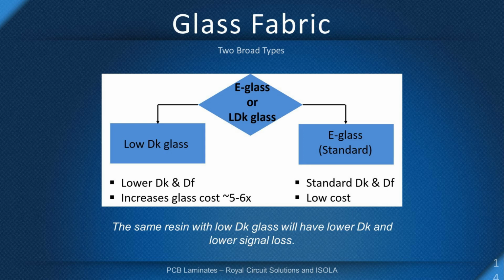All right, so as I had mentioned earlier, we have our 3 basic building blocks: our glass fabric, our resin, and our copper. There's going to be some other decisions you have to make with all 3 of these, and one of the first decisions you can make with the specific glass fabric is whether we want to go with a low DK glass or your standard E-glass. Now, for reference, a standard E-glass is going to have a DK of around 6 to 6.5, and your low DK glass is going to have a DK of around 4.5.